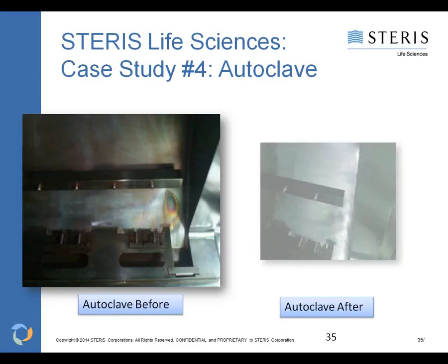So before I start addressing some of the questions that have come in, and I've seen a lot of great questions come in, just to summarize what Beth and Amanda were talking about, some of the important aspects of a really robust rouge and stainless steel maintenance program. The first key step is going to be a thorough cleaning with an alkaline detergent. What this does is it helps remove any organic residues, any kind of residue that would prevent the acid from coming in contact with that surface to really facilitate the derouging process or the passivation process. And we usually follow that up with a higher concentration, high temperature application of an acid-based product.